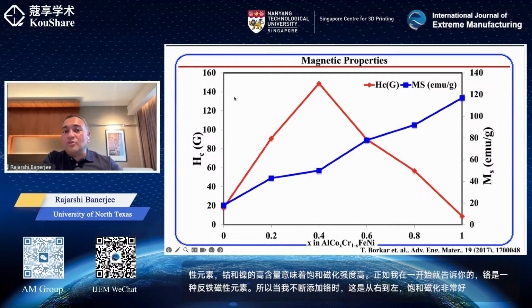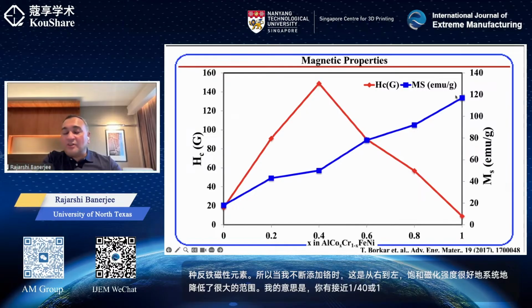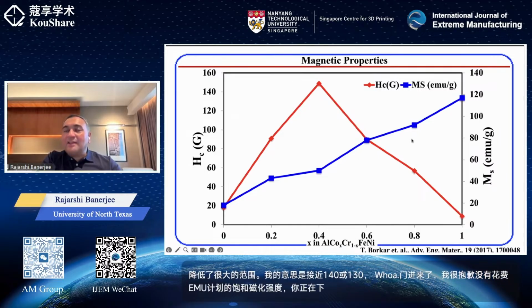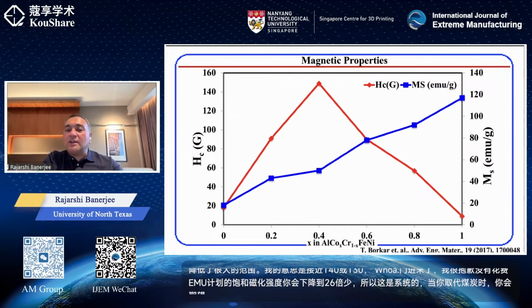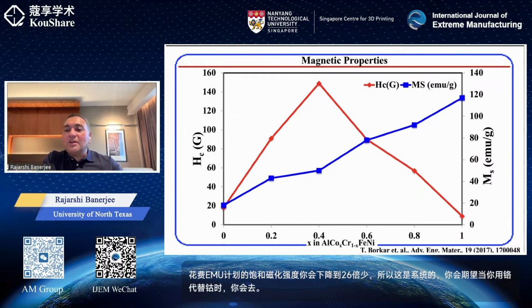You have a large range. I mean, you have close to 140 or 130 EMU per gram saturation magnetization. You're going down to 20, six times less. So this is systematic, and you would expect, as you replace cobalt with chromium, you are going to go to lower and lower saturation magnetization. What is not expected is the trend in the coercivity.